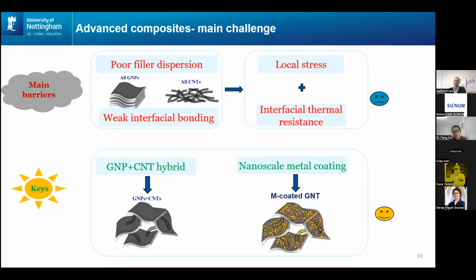There is also weak interfacial bonding between the filler and the composite. Both of these will result in local stresses and interfacial thermal resistance, which will harm the thermal conductivity improvement for the composites. So they are not good - those are the two main barriers we need to overcome.